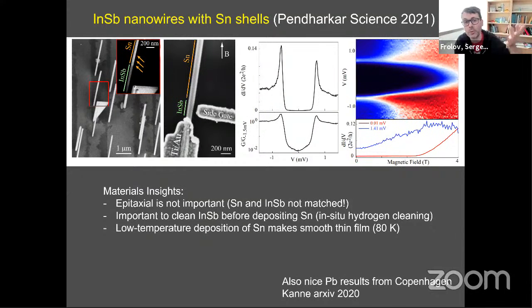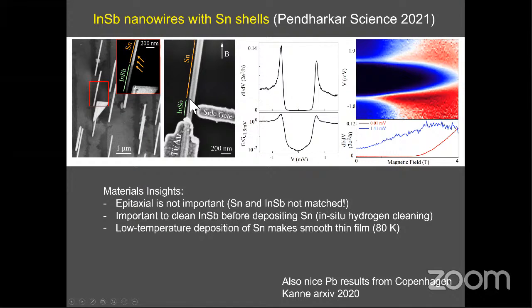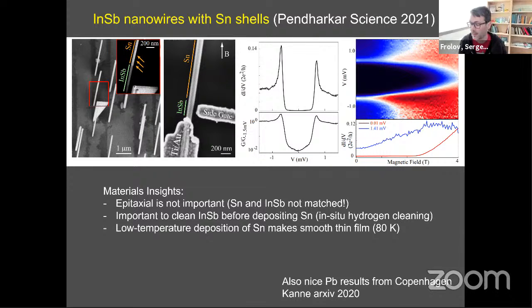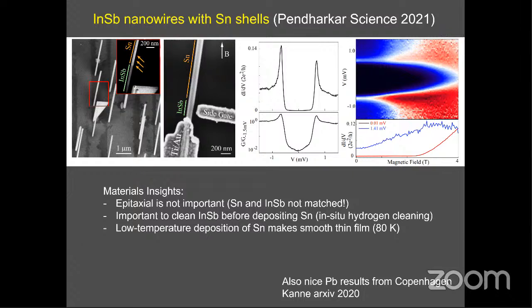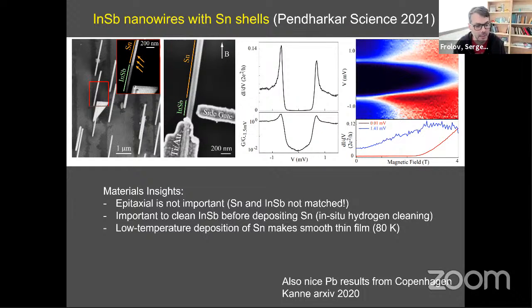I already showed you the tin wires, but here's some data where we've used the same indium antimonide wires, but we put a new superconductor on it. Well, tin is not new by any measure, but in this context, it's a new layer that we put on the semiconductor, and it was a collaboration with UCSB and Eindhoven and Grenoble. So it was a large effort. And yeah, the data look good.